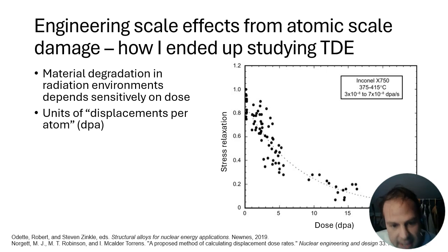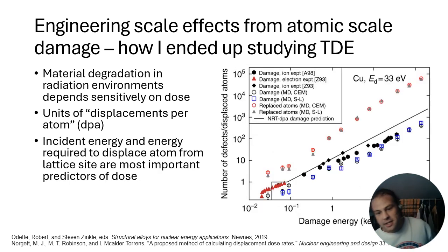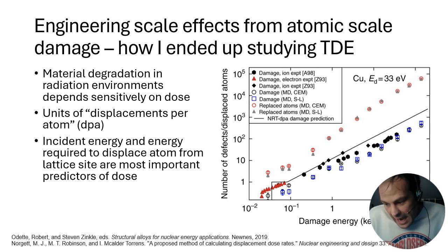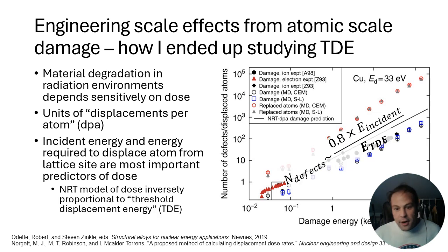And so then dose has these units of dPa. What is dPa? Displacements per atom. It's not exactly that 1 atom is displaced per 1 dPa, but roughly the energy required to remove an atom from its lattice site normalizes the energy imparted to an atom by an incident massive energy particle. So that is the ratio of the incident energy of your irradiating particle to the energy required to remove a particle from a lattice is going to be approximately the number of defects you create. And this is what we call dose. So the incident energy is controlled by our environment, but this energy required to remove an atom from its lattice is a material property.